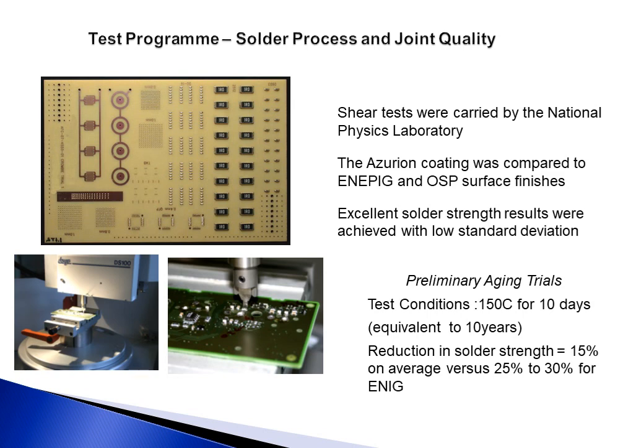We also got them to carry out preliminary aging trials where they stored the boards at 150 degrees C for 10 days, which is equivalent to 10 years. The joints on our board reduced by about 15% in strength on average, as opposed to 25 to 30% for the ENIG boards.